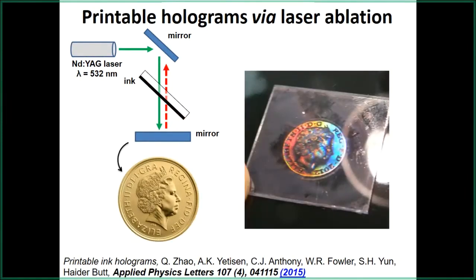Okay, this was another work which I conducted in Cambridge with Dr. Yun, and what we did over here was, rather than having a mirror, you can replace the mirror with a non-uniform reflective surface, and the light interference beams are dictated by this topography, and it gets printed into this layer. As you can see, the image of this surface gets imprinted into this surface.